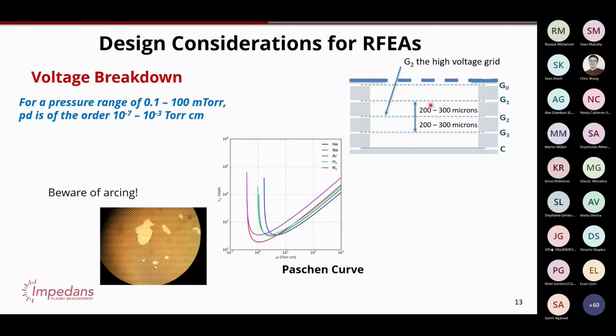So you need to make sure that these distances are still big enough and you're within an acceptable pressure range, such that you don't have breakdown inside the sensor. The other thing you can do is add insulating materials on the edges here to prevent breakdown along the sides. That's typically what we would do.